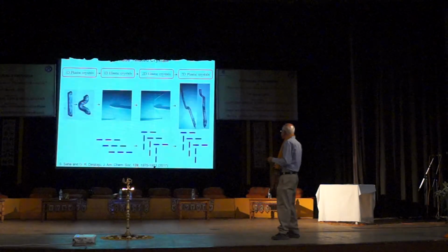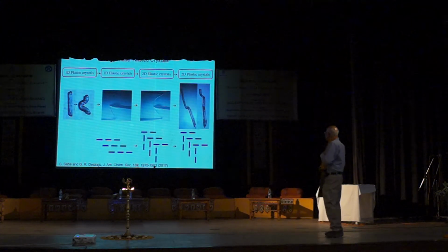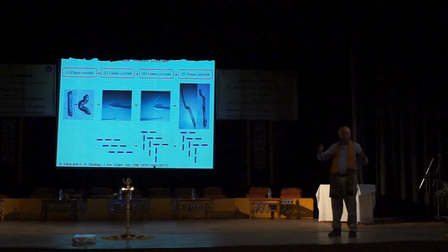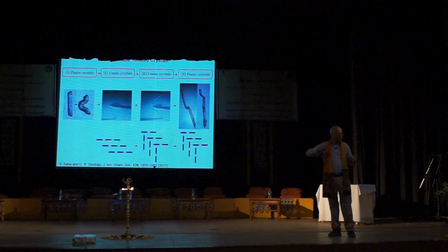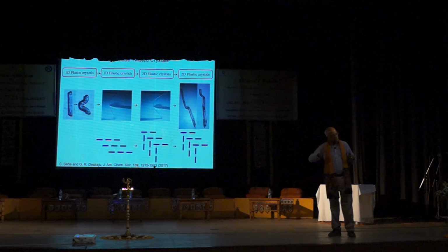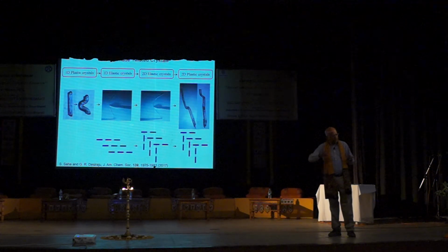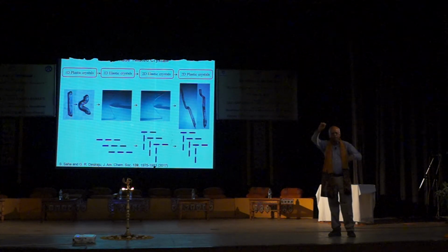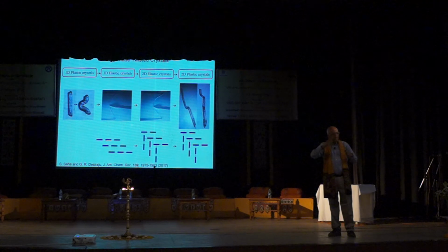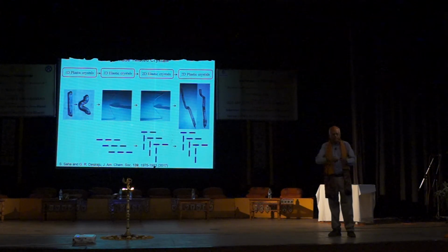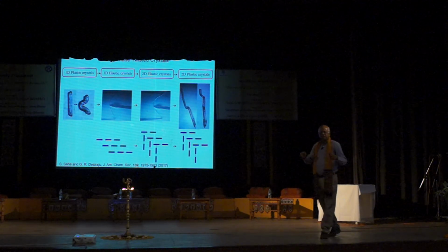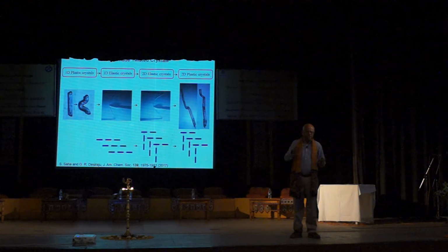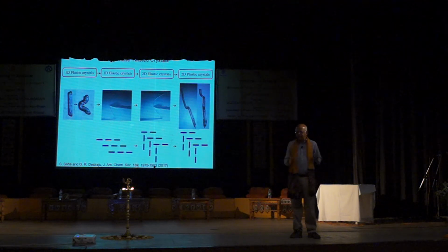Twistable crystal, this is again something recent that has come out in my lab. This is a whole wonderful area of crystal engineering where you can engineer mechanical properties. If you have a balance of interactions of a certain type, you get crystals that are plastic. Plastic means you bend it and then it doesn't go back. If you have a different balance of interactions, it's elastic. When you bend it, it jumps back. Most crystals of course are neither plastic nor elastic, they are just brittle. If you take a crystal and do all these tricks, it will just break.